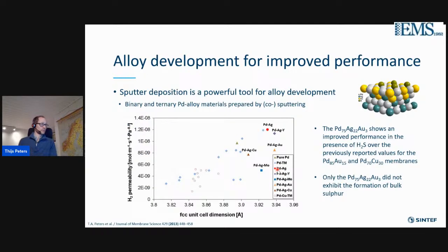In a previous project, we tested a lot of different alloys based on palladium silver, but also based on palladium copper, to check which alloys have a better H2S resistance, but also which alloys can be improved in terms of flux. Then we found that especially palladium gold or palladium silver gold has a very decent flux, while it prevents the formation of bulk sulfides. So palladium gold and palladium silver gold are attractive alloys to be used for high temperature hydrogen separation processes with palladium membranes.